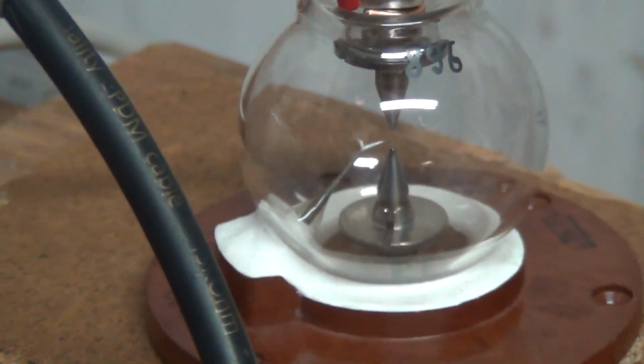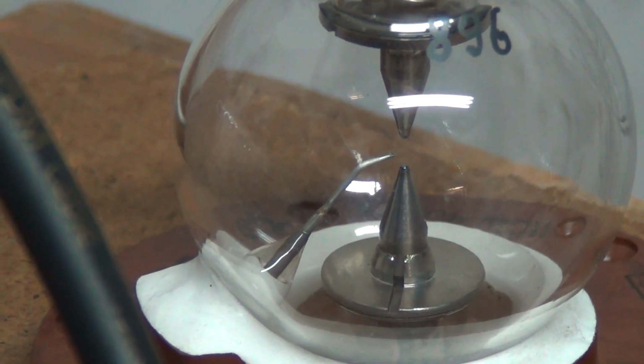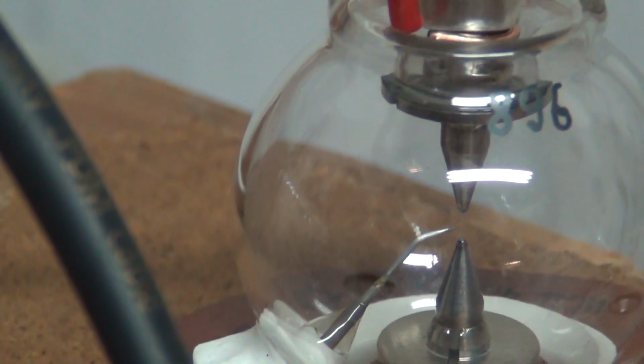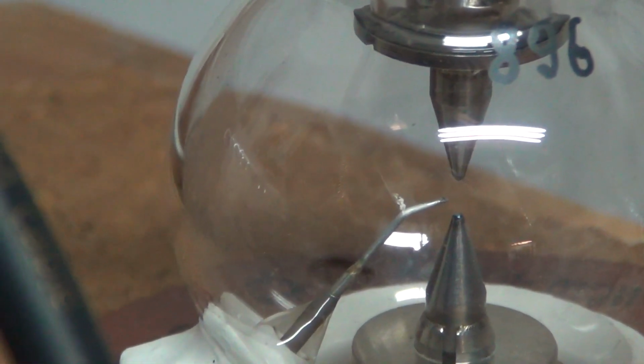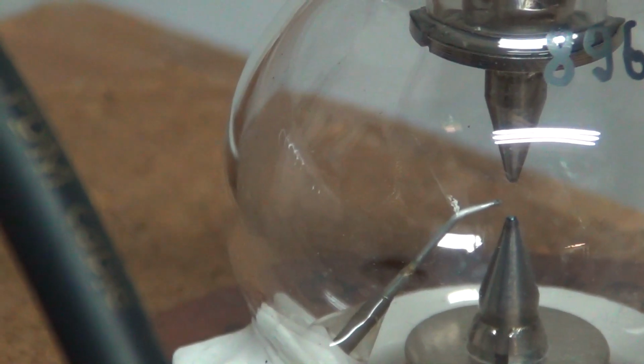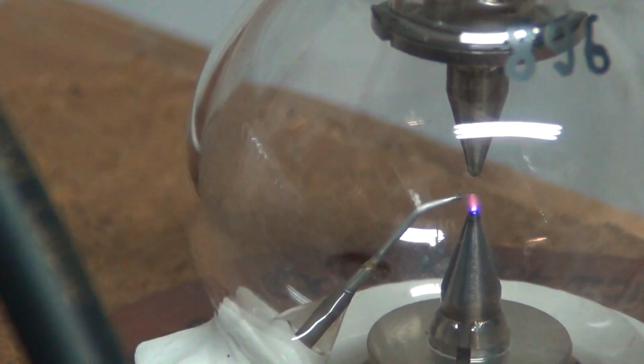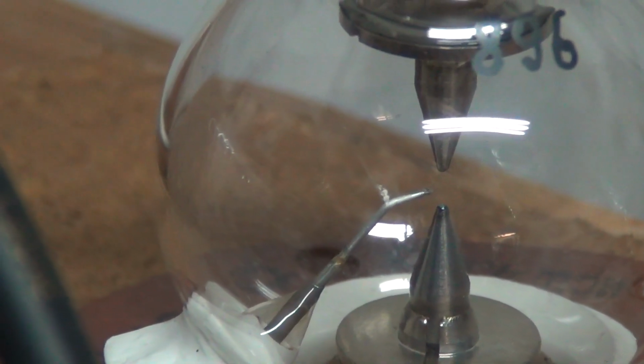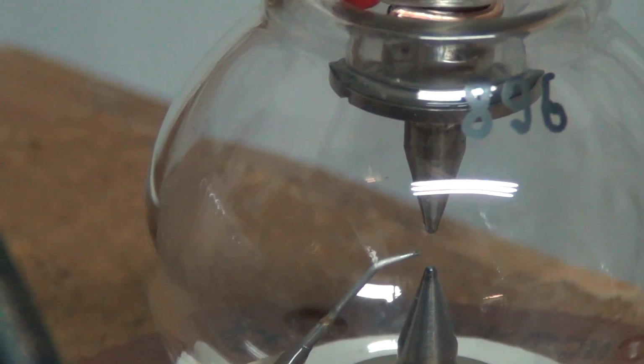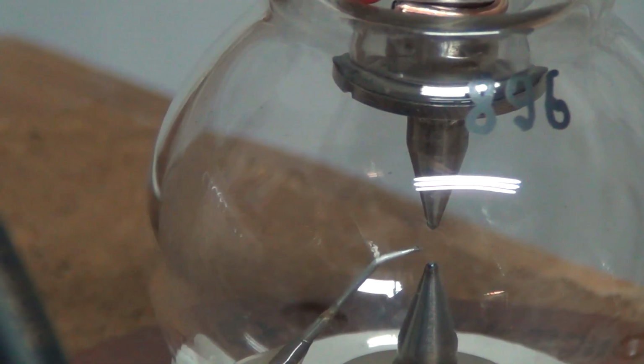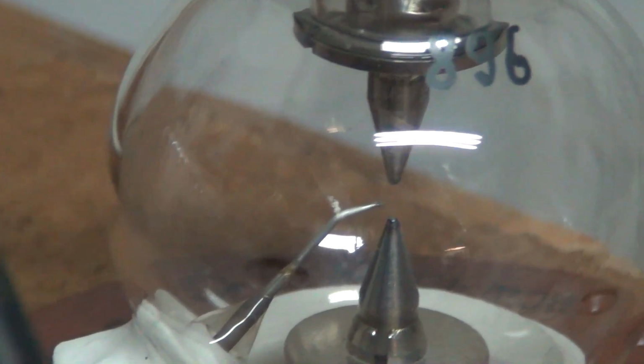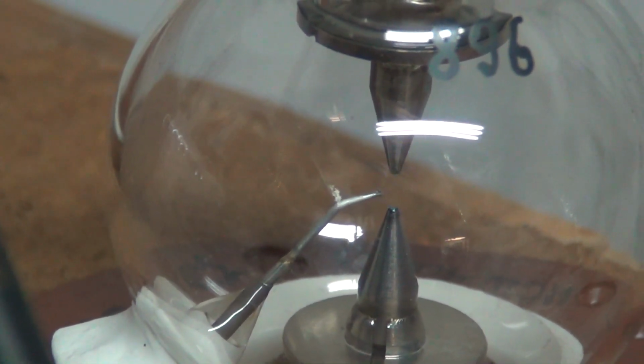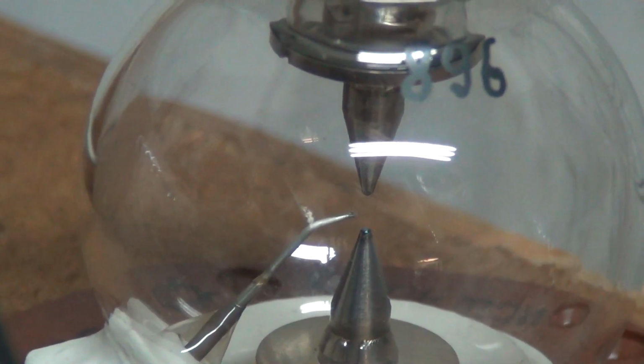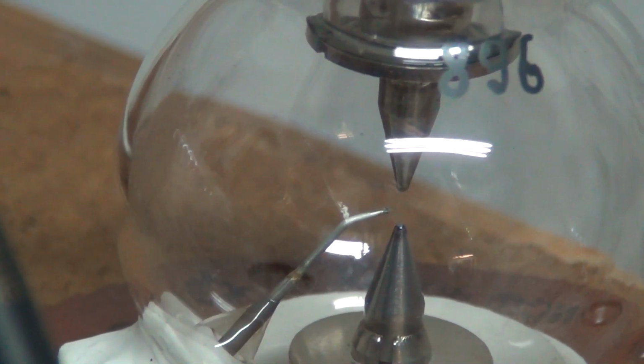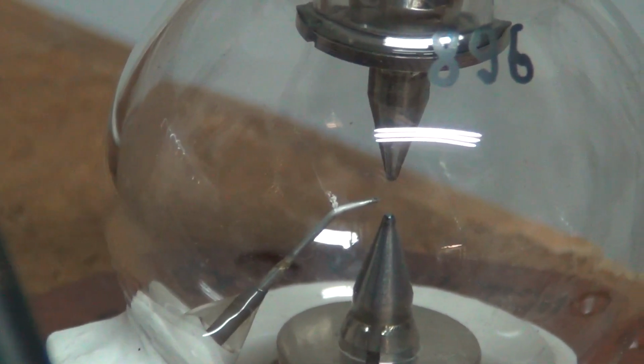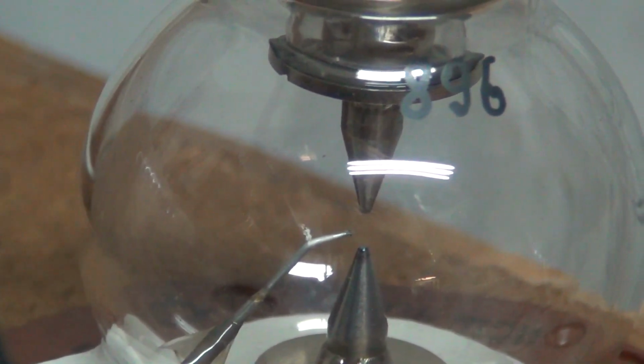I decreased the step to 5 kilopascals, and even with this 5, it can be seen that each kilopascal now gives more surface covered by this breakdown. And respectively, the surface which transmits some interference is becoming wider and wider.